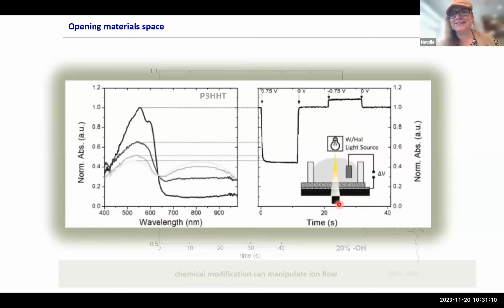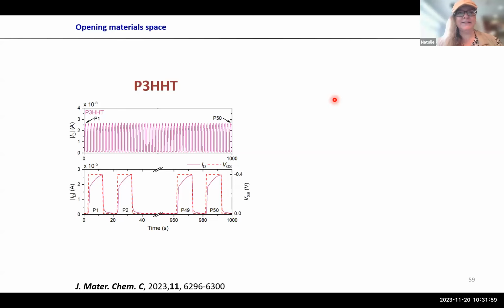So here you see the schematic. You shine light, you have the film, you have a reservoir with your electrolyte, you apply the bias, and then you see really what happens to the absorption. I should have brought this slide first. While you apply different bias. So here you apply positive bias. You see you have bleaching of your main absorption, but you get here the polaron band, and vice versa. If you stop applying the bias, it goes back, but you have to apply then negative bias to really get all ions out. And you can do that.